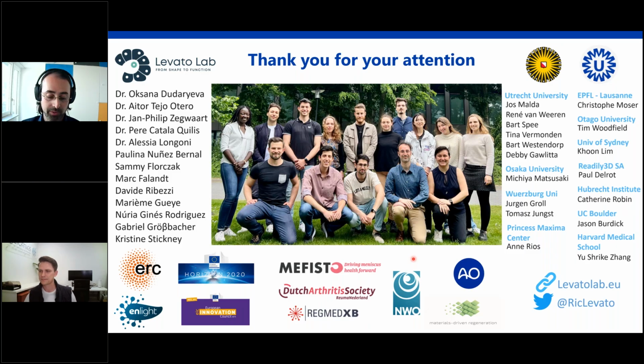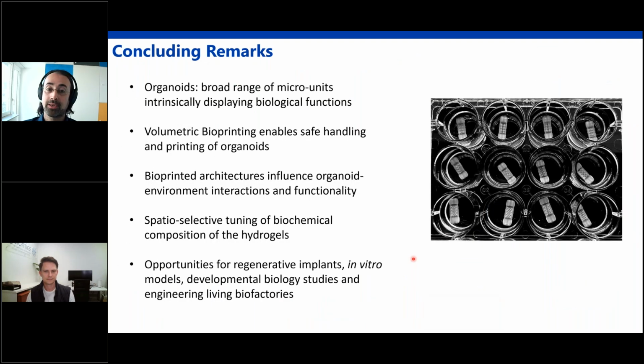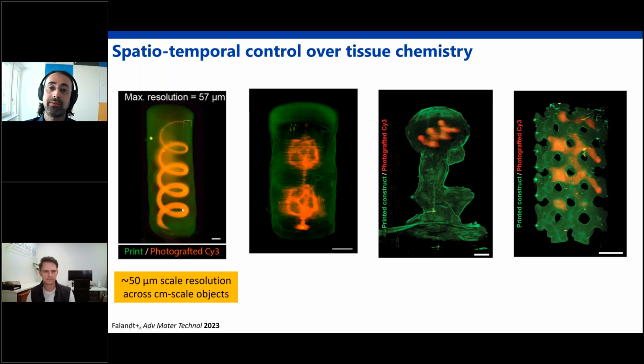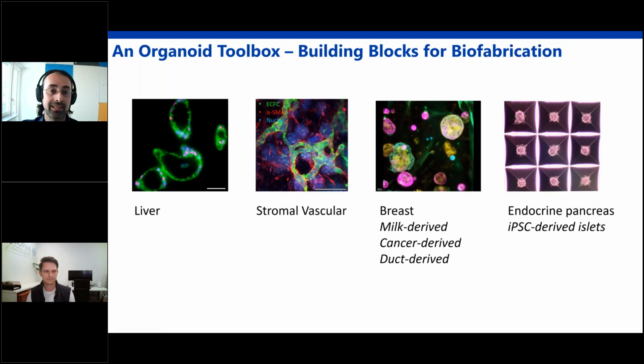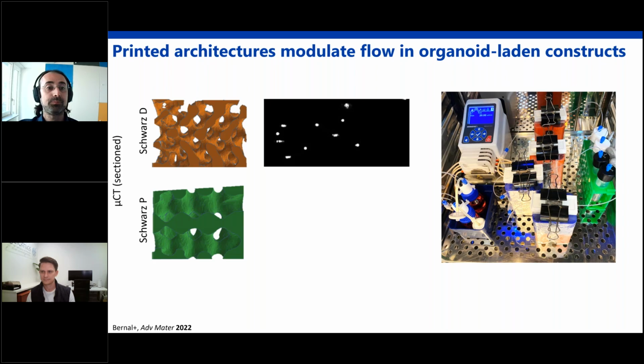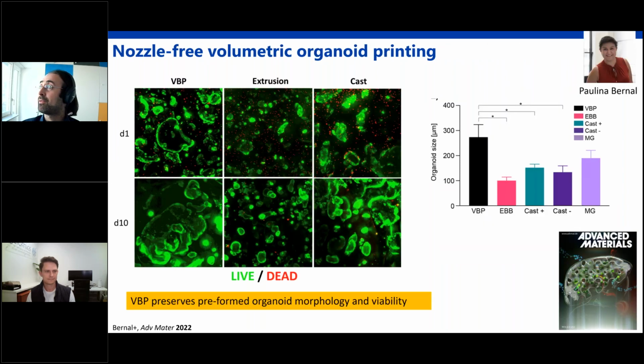Right. That's a fair point, because as I mentioned, they are quite fragile. The advantage here is that we don't need to. We can just load them with the serological pipette, so that we don't have the tip of the micropipette there fragmenting the organoids. So essentially we add our organoid suspension, which is sedimented into a Falcon tube. We add on top of it our hydrogel, and very slowly with the serological pipette, we mix them up, and then we pour them into the glass vial.